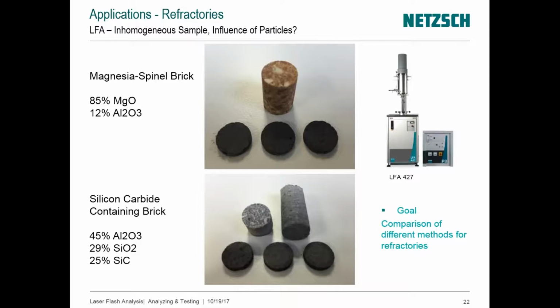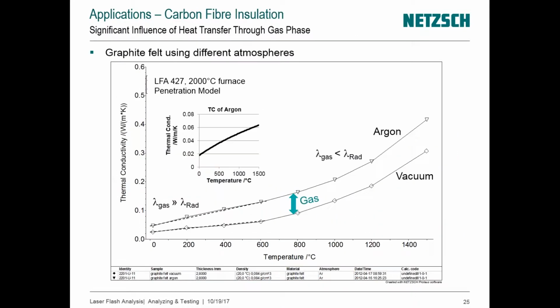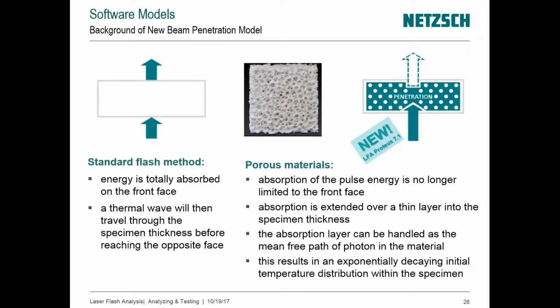In the last case, right now we're looking at a very porous type of ceramic that would be your material of interest. Simply to say that because we can apply the penetration model, it is fairly expected that the measured diffusivity and or measured conductivity will be accurate, simply because we are using the appropriate model. Very important to insist on that, because many times it is overlooked. You might be able to get away with it if the porosities are not too pronounced. But when it starts to be important, 5% porosity or more, it's very critical to account for the beam penetration.